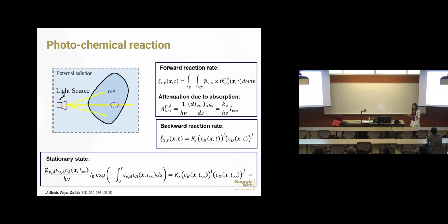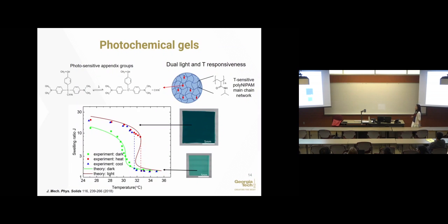This is general in chemistry, but here I want to emphasize the difference is now you can't simply solve this equation independently. It has to be considered coupled with deformation. The reason is the following. You can think, as you shine light to the material, it generates a chemical reaction, right? This chemical reaction will draw water coming in and out, and that will dilute your chemical composition, and at the same time shift your chemical equilibrium. So it's a coupled process. We really need to couple with mechanics to solve this whole behavior of the material.